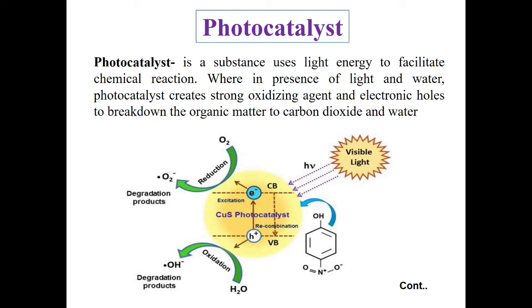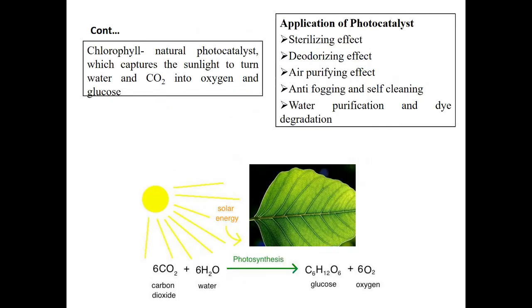4-nitrophenol, and that 4-nitrophenol gets degraded and oxidized to form the degradation product along with the reduction product. That material can be easily degraded with the help of this copper sulfide photocatalyst in the presence of visible light. Applications of the photocatalyst: it has a sterilizing effect, deodorizing effect, air purifying effect, anti-fogging, self-cleaning, water purification and dye degradation.